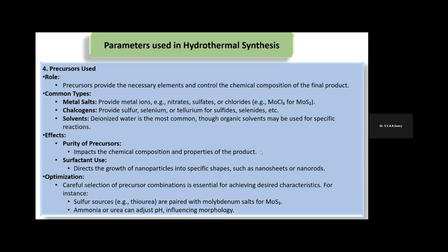Then the last parameter is precursors, which are used to make the nanoparticles. Precursors provide the necessary elements to control the chemical composition of the final product. For example, metal salts like nitrates, sulfates, or chlorides give metal ions. Example, MoCl5 for making MoS2 nanoparticles. Similarly, chalcogens provide sulfur, selenium or tellurium for sulfides, selenides, etc. The solvents can be deionized water, although we can also use organic solvents for specific reactions.